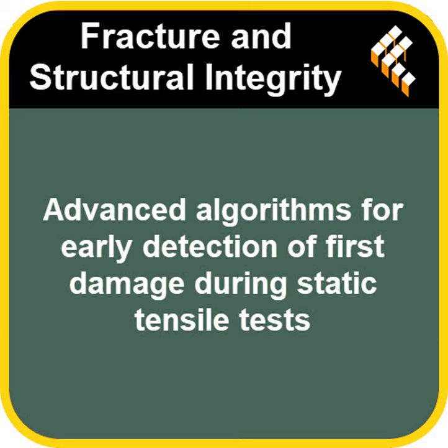Right. So phase 1, as you start stretching it, the temperature actually drops slightly in a linear way. That's the thermoelastic effect Lord Kelvin talked about. Basically, it cools a tiny bit as it stretches elastically, like stretching a rubber band quickly. Sometimes you feel it cool. Same idea. Okay, makes sense. Then phase 2.